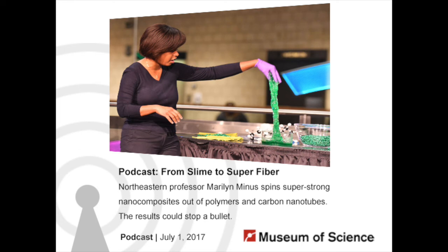Yeah, definitely. So out of all the polymers that we typically use today, like polyethylene, polypropylene, nylon, PET, or polyester, a lot of those polymers are very much wiggly chains, just like the polyvinyl alcohol or the slime polymer. And so what we're trying to do is take the recipe that we've learned from the polyvinyl alcohol or slime by adding nanotubes in it and making it straight to make that superfiber, and seeing if we could come up with a universal recipe that we can then use with all of these other polymers. So in my lab, we're working with polypropylene, polyethylene, nylon, polyester, polyacrylonitrile, or acrylic as most of us know it. So we're working with all of them to try to make a universal recipe.